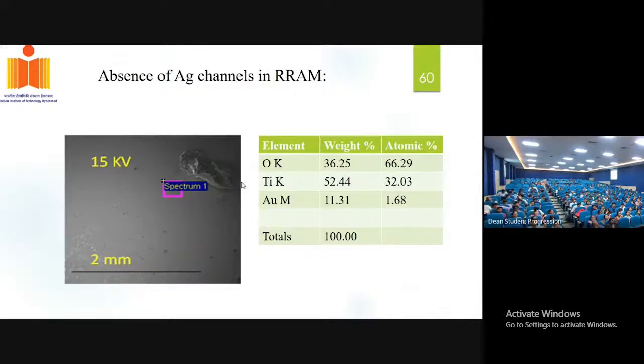Sometimes what can happen is that the Ag, the silver electrode that we keep on top of the device, can also diffuse from top to bottom, and that can also give this kind of characteristic. To prove that, we also have done depth profiling using scanning electron microscopy, secondary electron microscopy, to see up to what levels the silver atoms are diffused within the thin film. What we could see is that up to the depth level of 1 micrometer, we don't see much diffusion of the silver atoms within the thin film. So from this, we confirm that the resistance switching characteristics that we have obtained in the titanium dioxide based Ag device are because of oxygen defects. It is not because of the Ag atoms that diffuse in the device.